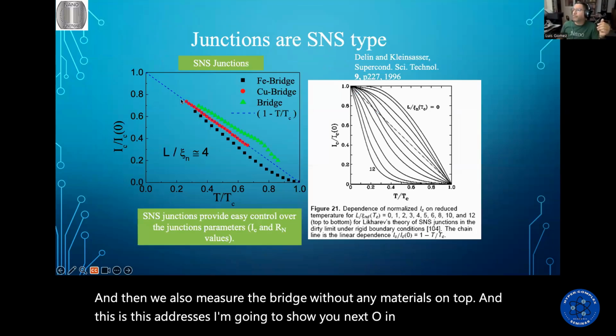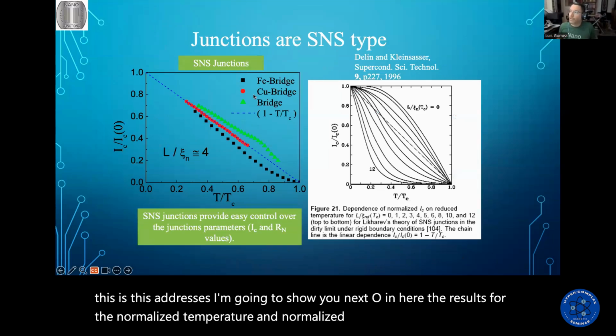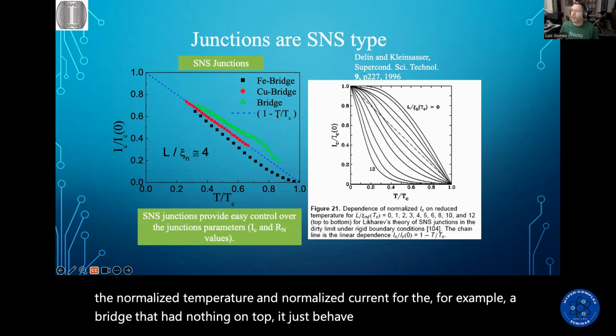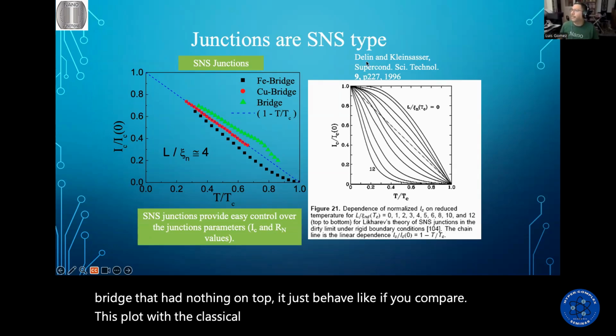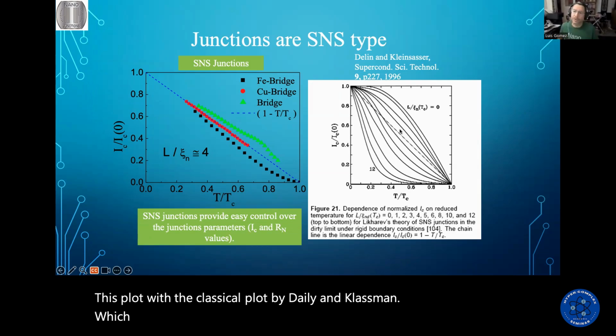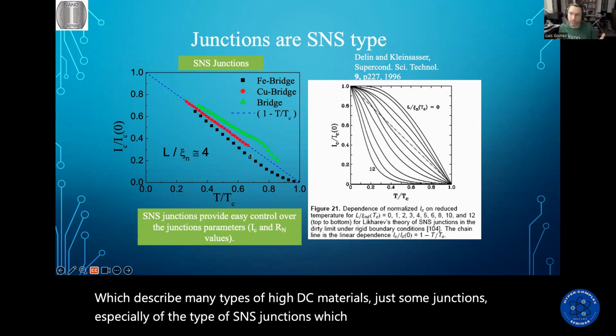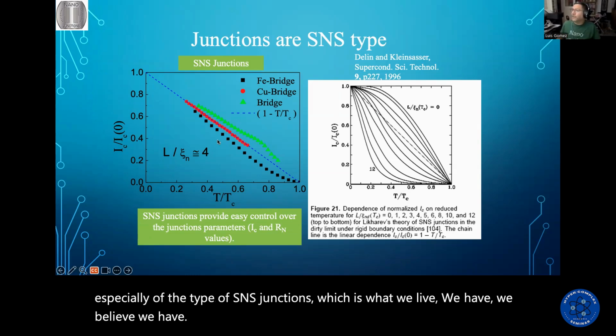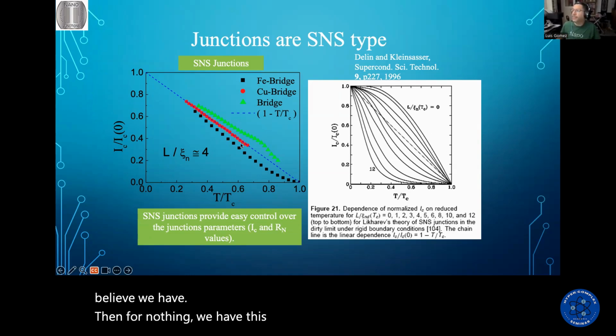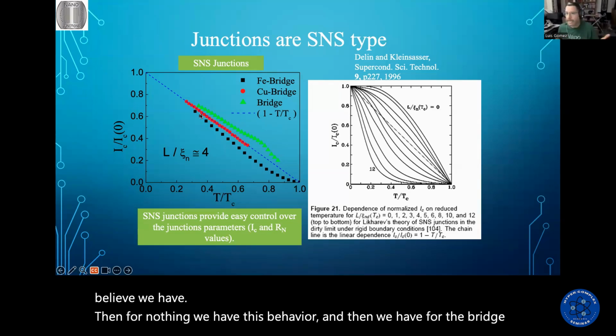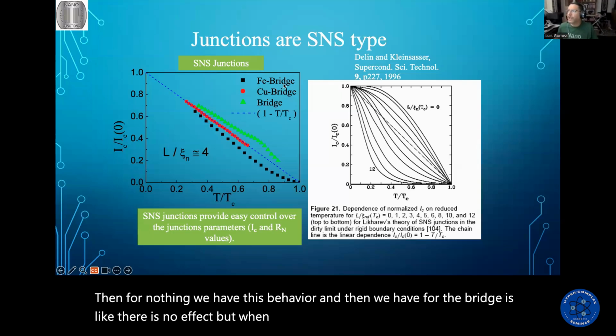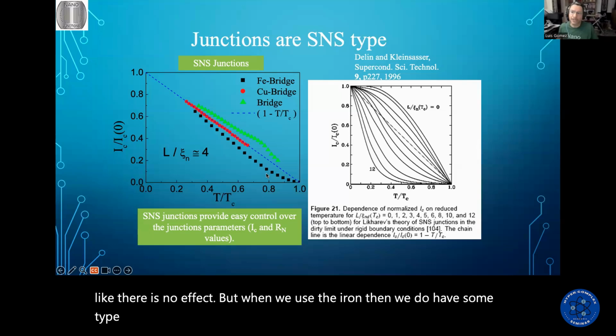So here are the results for the normalized temperature and normalized current. For example, a bridge with nothing on top behaved just like the classical plot by Delin and Kleinsasser, which describes many types of high TC materials, Josephson junctions, especially of the type of S-N-S junctions, which is what we believe we have. For nothing, we have this behavior, and for the bridge it's like there is no effect. But when we use the iron, then we do have some type of junction behavior.